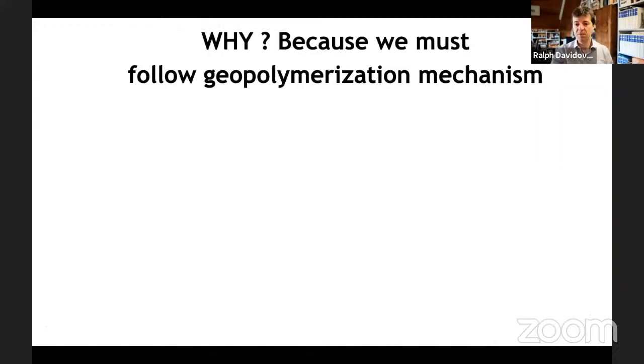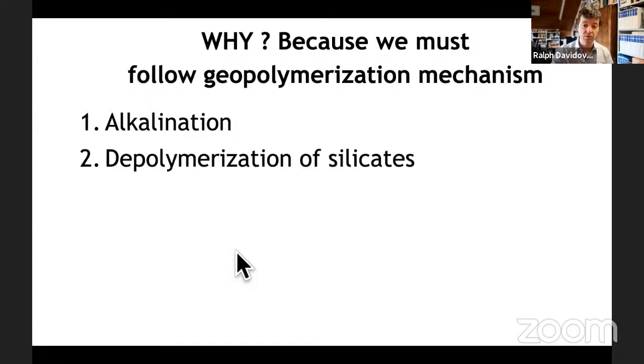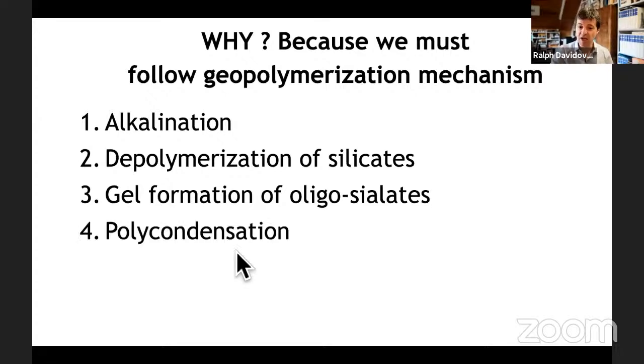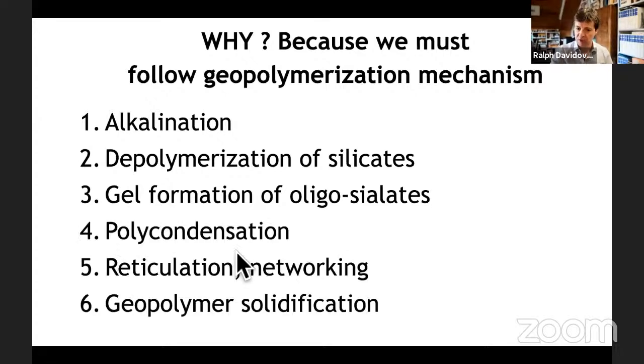Why? Because we must follow the geopolymerization mechanism, which starts with alkalination. Alkalination is not alkali activation, nothing to do. We continue with depolymerization of silicates, gel formation of oligo-sialates, polycondensation, reticulation networking, geopolymer solidification. So they refuse to understand and follow the principles of polymerization. How can these people be able to develop commercial applications, finding the good formula, solve problems if they don't understand the true chemical mechanism? They will fail.